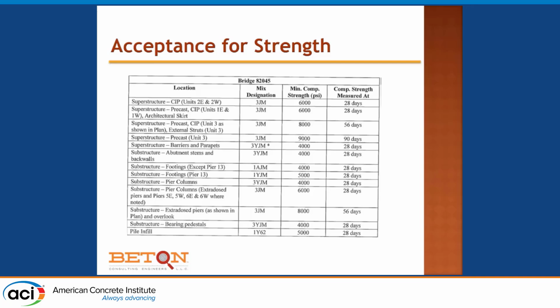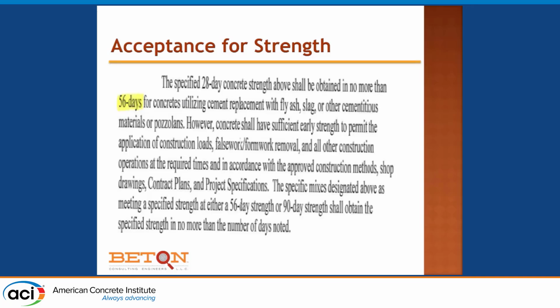And in fact, the specification, and you can tell by the crude nature of this slide, a picture of the specification itself. And it says, you shall obtain the strength for no more than 56 days if you use cement replacement with fly ash, slag, or other cementitious materials.